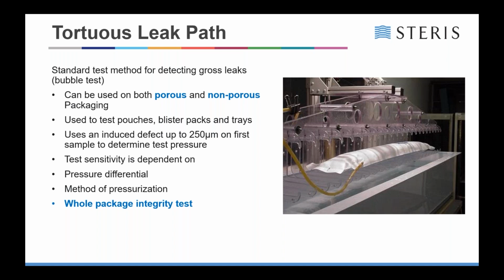But as I said, its disadvantage is that its sensitivity is only down as far as 250 micron, which is pretty much the equivalent of the thickness of a human hair. And again, it depends on the pressure that you can get in there. So for the likes of Tyvek or paper, they have their own natural breathing points, which are around 2 to 2.5 kPa, possibly 3 kPa, whereas a defect around 250 micron will be detected between 1.5 kPa and 2 kPa. So it's quite easy to detect.